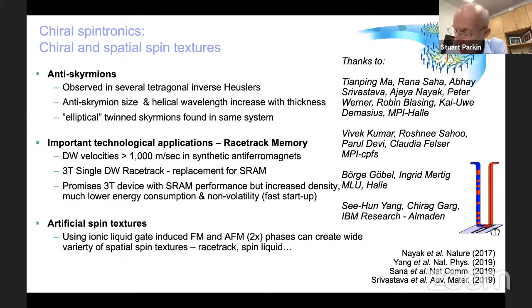This is certainly possible. And to detect them similarly, because the surfaces are magnetic, unlike a real antiferromagnet, where there's no net magnetization on the surface, usually because of steps. In principle, it's possible in, let's say, iridium manganese 3, you would expect to see a surface which is magnetic, but it's on the atomic scale. So steps means in aggregate there's nothing. But in the racetrack, because the upper layer is ferromagnetic, then the surface is magnetic, and you can just detect the domain walls by, for example, magnetic tunneling or other effects. So it's relatively straightforward. Okay, good.